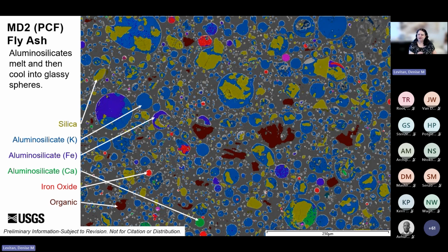So this is the same picture again as 2 slides ago, now with that similar color scheme applied for the different composition. Again, silica in olive color, aluminosilicates in various shades of blue to green for these calcium-rich ones, red iron oxides, organic materials. So to note here, some of the differences beyond just the shape of the particles, the spheres, are that we see fewer independent, or at least large independent silica particles. They tend to be more trapped in big chunks within these aluminosilicate melt spheres. We also see now these calcium-rich aluminosilicate bubbles or spheres, and fewer of these purple calcium sulfates.